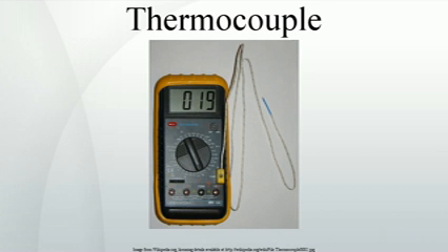Inhomogeneous sections may see exposure to increased temperature gradients from hot to cold as the inhomogeneous section now passes through the cooler refractory area, contributing significant error to the measurement. Likewise, an aged thermocouple that is pushed deeper into the furnace might sometimes provide a more accurate reading if being pushed further into the furnace causes the area of inhomogeneity to be located in an area of the furnace where it is no longer exposed to a temperature gradient.